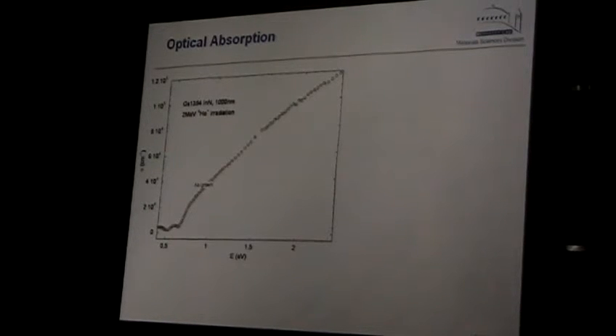So now, what is happening with optical absorption? Because now we are moving this Fermi energy in the conduction band. So let's take indium nitride. Indium nitride should have a gap, as I mentioned, of 0.7 eV, this low gap, and absorption goes up when you increase the energy. Then you irradiate it slightly, and what you see is an absorption edge shifted to high energy. If you irradiate it more and more, the absorption edge shifts to higher energy. Finally, it saturates. Those last two sets of points are almost the same, although the irradiation dose is different.